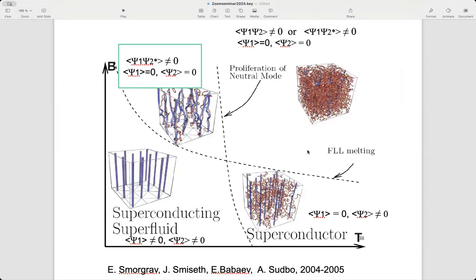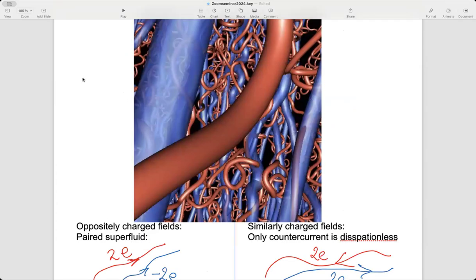If one writes it in terms of the order parameter, there are four possible phases. One of the possible phases is where each order parameter, each of the order parameters of fermion pairs, electron pairs, or Cooper pairs, is non-zero. In another case, both order parameters are zero. And the most interesting case is the one where individually the order parameters are zero, but the product is non-zero. If one talks about hydrogen-type systems, the non-zero order parameters are actually a pair of electrons and a pair of protons. So essentially, physically, what does that mean?